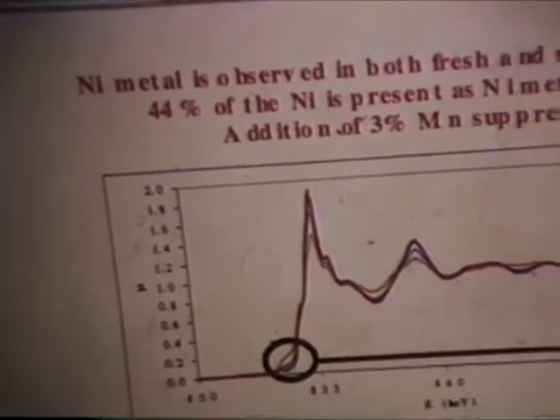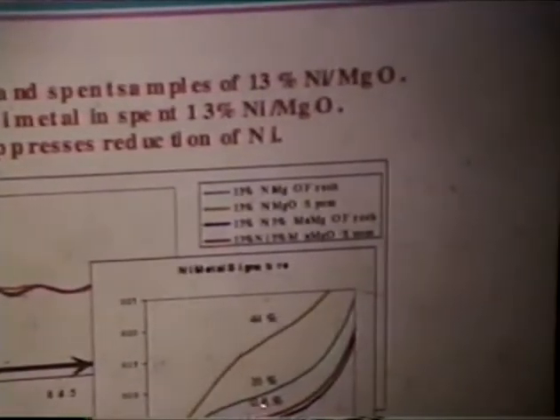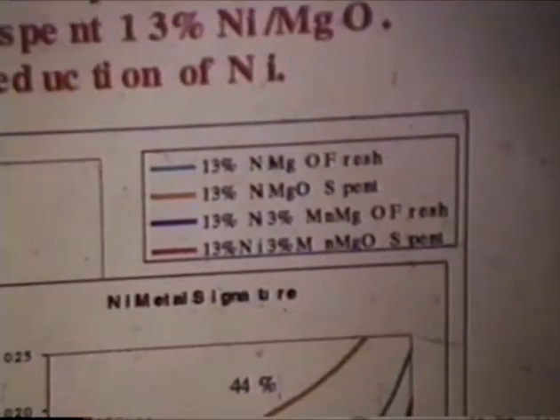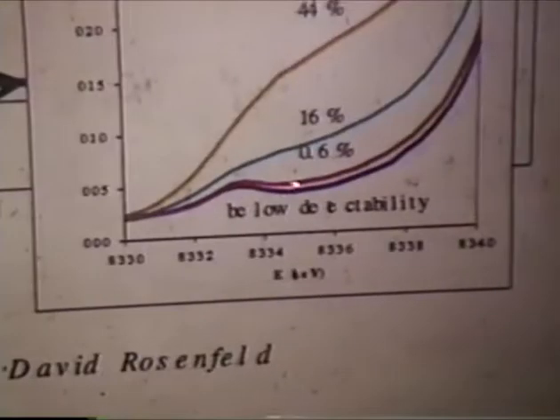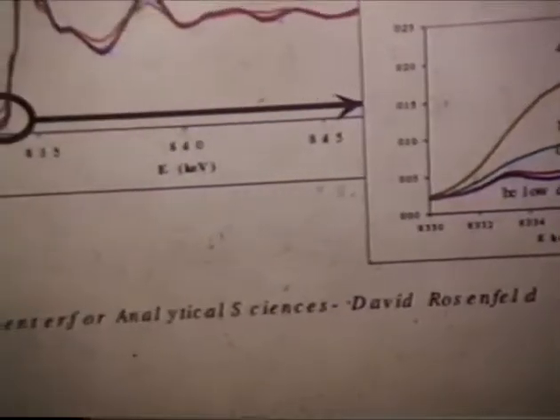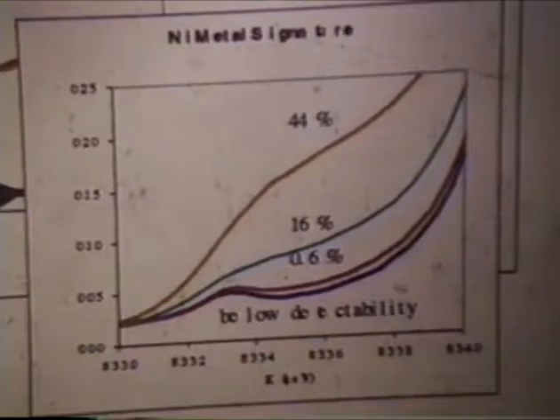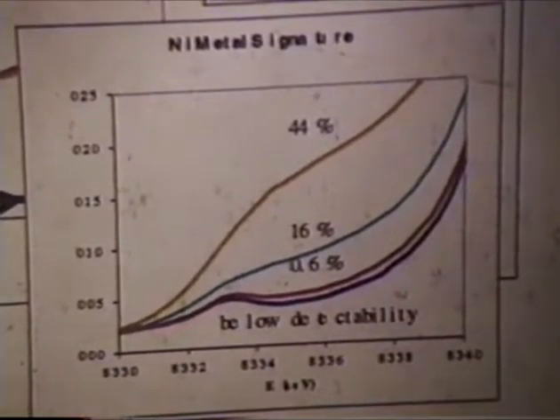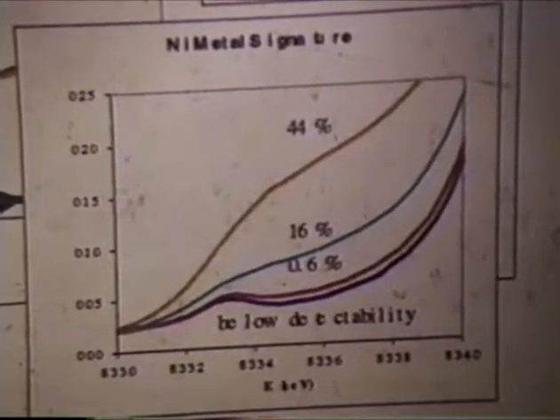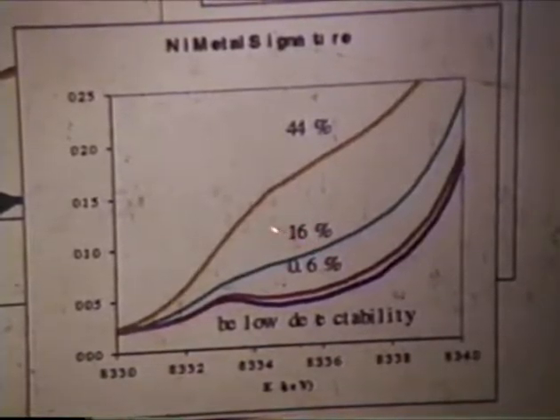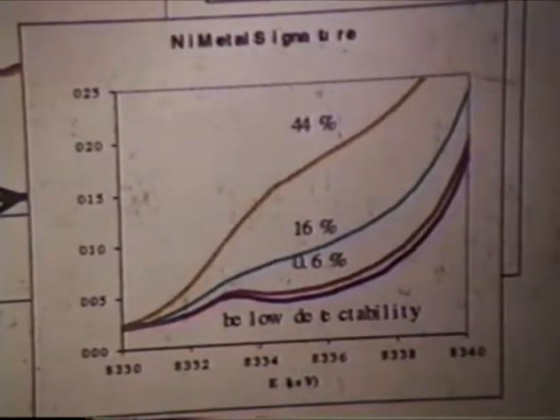And the spectra are shown here. It's probably easier to look at this section here. The dark lower blue curve is a fresh catalyst with a manganese promoter in there. After it's been used in syngas production, the red line curves on that spectra, and it's showing you that 0.6% of the nickel in the catalyst becomes reduced. Whereas the unpromoted catalyst, even before you do syngas, you already have 16% nickel metal, and you might wonder, why is that?